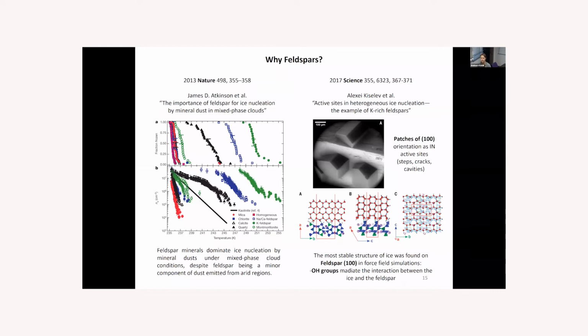So why feldspar? Why not any other minerals which are naturally occurring on Earth? Well, it's already been shown in a 2013 Nature paper by James Atkinson that feldspar minerals dominate ice nucleation by mineral dust. And they showed it by comparing the potassium feldspar, shown here in green, with other minerals and surfaces such as mica, chlorite, calcite, and quartz. They compared also the homogeneous nucleation of ice. And as you can see, the potassium feldspars show the highest efficiency in freezing of water and ice formation at the highest temperature. The difference is quite huge between potassium feldspar and all of the others.